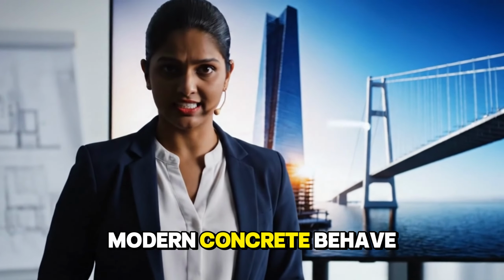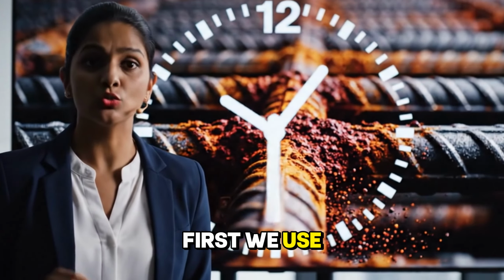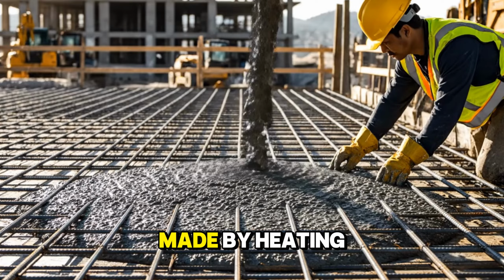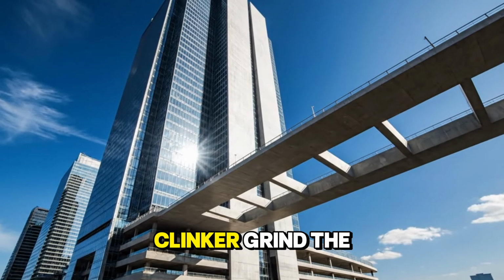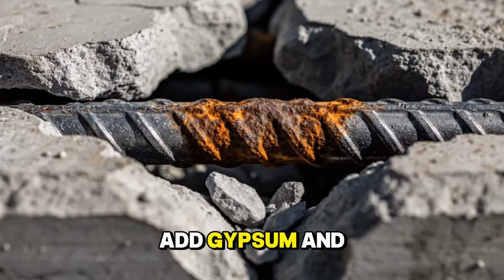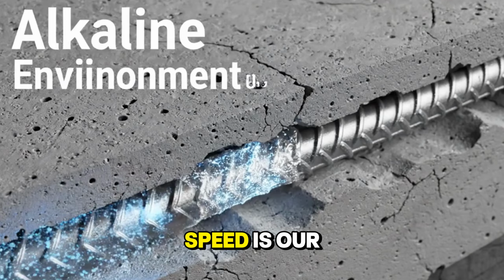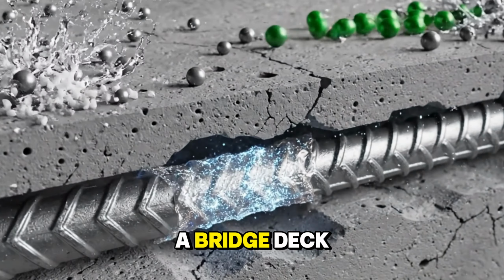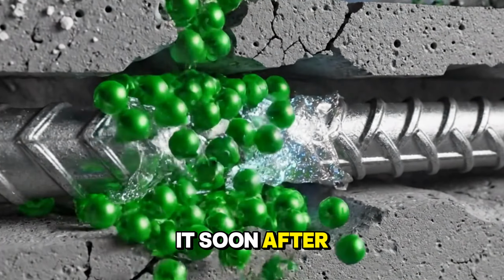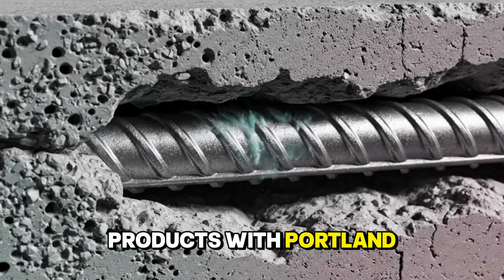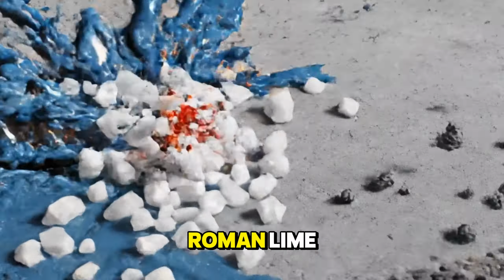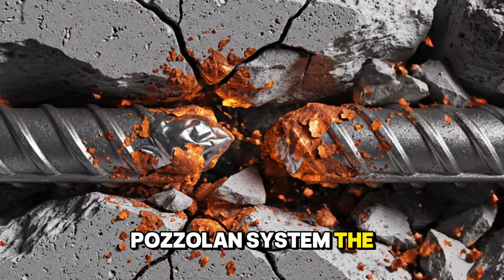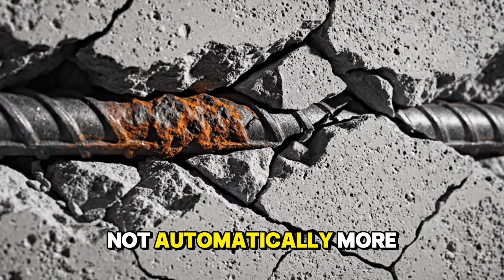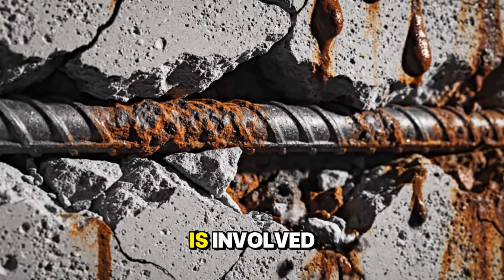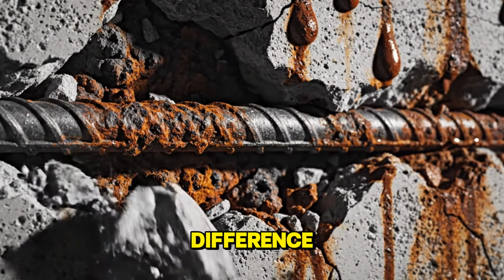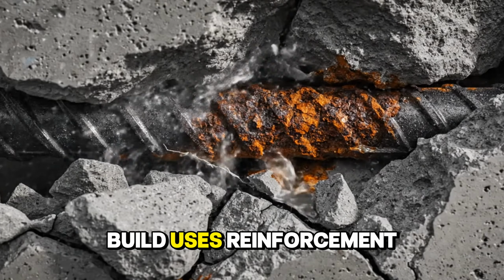So why doesn't modern concrete behave like that? First, we use a different binder. Portland cement is made by heating limestone with clay until it forms clinker. Grind the clinker, add gypsum, and you get a powder that hydrates fast. Speed is our superpower. We can pour a bridge deck at dawn and drive trucks over it soon after. But the hydration products with Portland cement create a different microstructure than the Roman lime, pozzolan system. The result can be strong and stiff, but it is not automatically more durable, especially when steel is involved. And steel is the second key difference. Almost everything we build uses reinforcement.